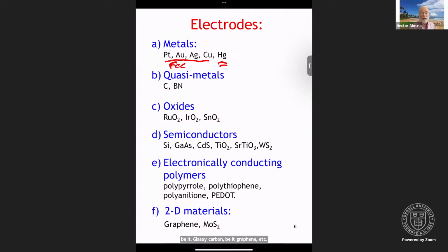Conducting metal oxides, these are typically non-stoichiometric oxides. The typical ones, ruthenium oxide and iridium oxide, are used as oxygen evolution catalysts. Ruthenium oxide is part of the so-called dimensionally stable anode that is used in the chloralkali industry. Tin oxide is also typically fluorine doped, or FTO, fluorine doped tin oxide, used also as a conducting oxide. It also makes a reasonably transparent film, so you can make transparent electrodes, so you can do spectral electrochemistry in optical